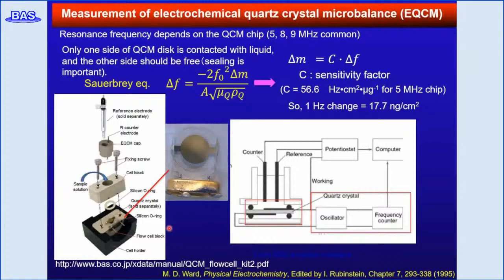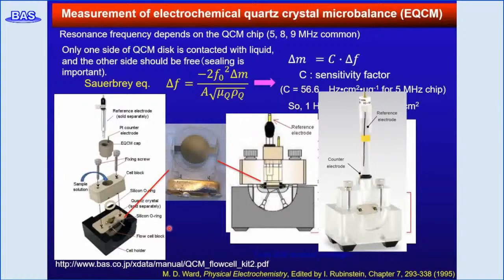From several equations, we can calculate the mass change. For a 5 MHz QCM chip, the sensitivity factor is 56.6 Hz cm²/µg, so a 1 Hz change corresponds to 17.7 ng/cm² mass change. For EQCM-D measurement, the frequency counter is replaced by a network or impedance analyzer. Recently, QCM equipment is commercially available that can measure the frequency response of admittance, conductance, and susceptance.